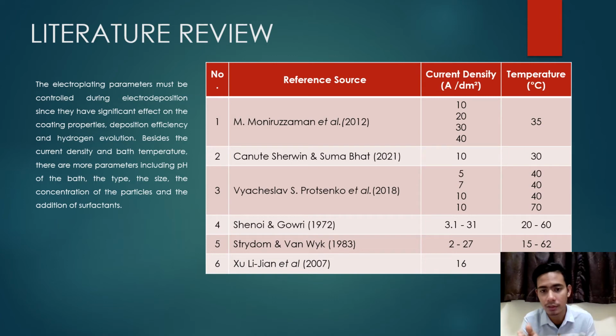For example, for the Moniruzzaman et al. 2012 journal, 4 current densities are used and only 1 temperature. For the Shenoi and Gowri 1972 journal, in the experiment, they use the range of 3.1 until 31 current density and 20 to 60 temperature. What we can conclude is that different current densities and temperatures used for the electrodeposition method give different experiment results.